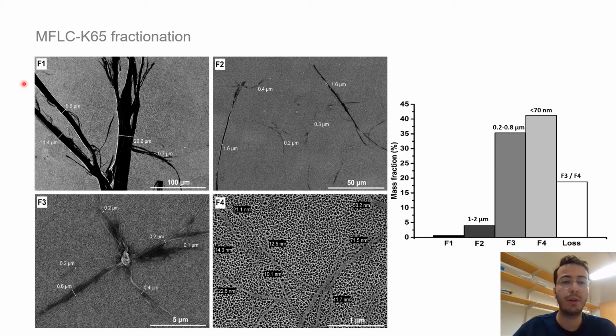And I have prepared fraction 1, fraction 2, fraction 3, and fraction 4. You can see these fractions, or F1, F2, F3, F4 for the fibrils here, and you can see the widths of fibrils which retained on the meshes. And in fraction 1, you can see this is quite large fibrils with a really high width.